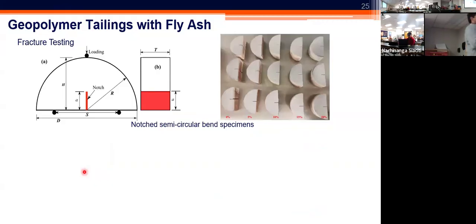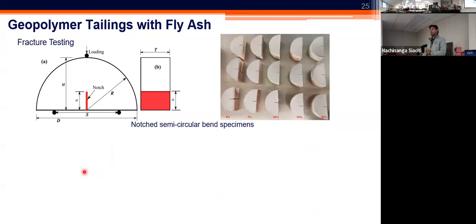All right, but evaluation of the behavior of the material would not be complete after only compressive strength testing. In many cases, it's very important to evaluate the behavior of the material and its resistance to fracturing. That is a type of test that we consider fracture mechanics testing. An analogy is that little chip you get on your windshield, and you ignore that chip, and eventually after maybe a season of winter and wetting and drying, that chip starts to grow and turns into a big crack, right? That tendency for the chip to become a major crack is related to the tendency of the material to resist the fracturing or allow the fracturing to happen. So we can evaluate that resistance or tendency by intentionally performing fracture testing.